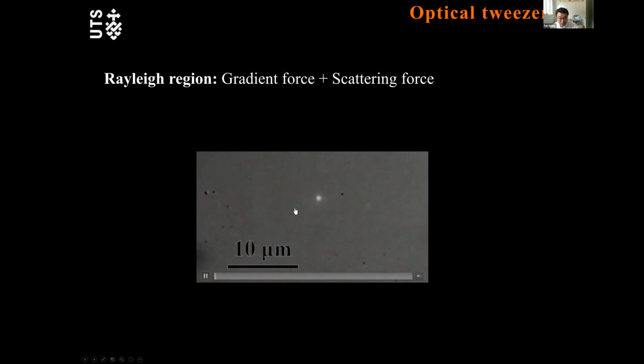So this is one example. We can trap one 50 nanometer gold nanoparticle, and we can move it really fast. But the challenge is that you need to use really high power. For this one, we use about 100 milliwatts, which is quite a lot.